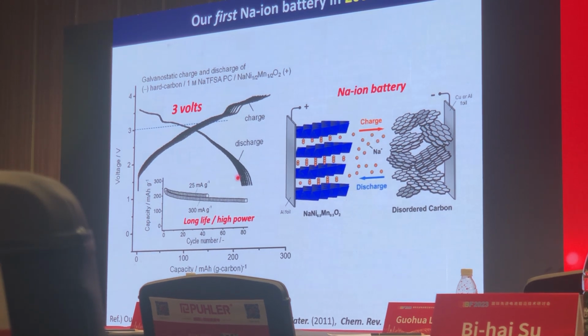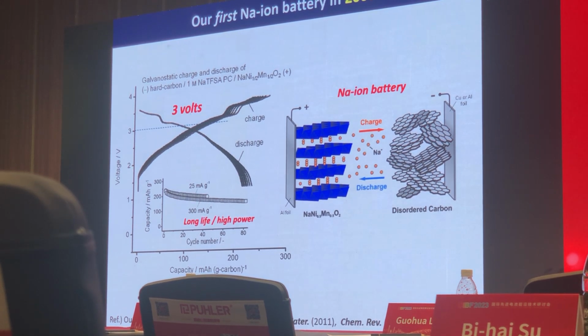So in 2009, we succeeded in the demonstration of a sodium-ion battery based on hard carbon and nickel manganese oxide, and this shows an average voltage of 3 volts and acceptable charge-discharge cycle life, by developing a new electrolyte solution for sodium-ion battery.